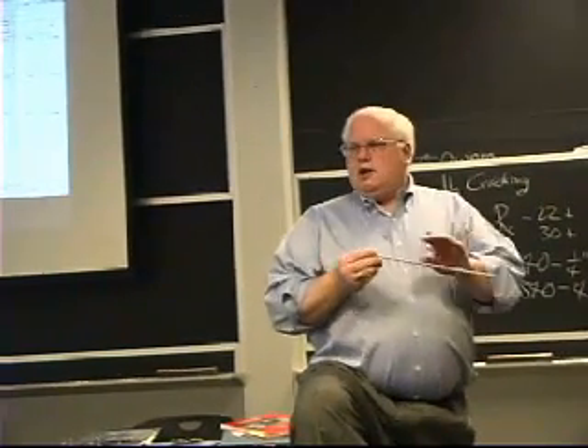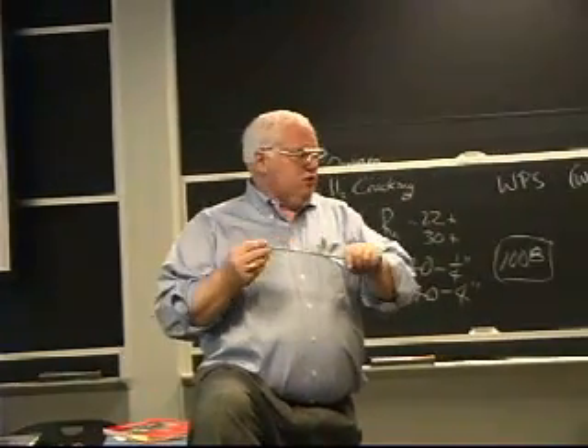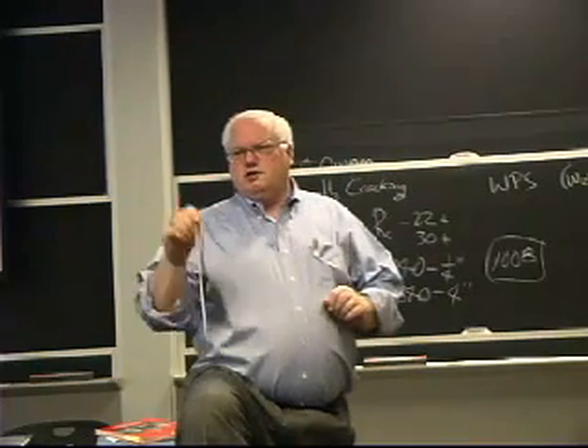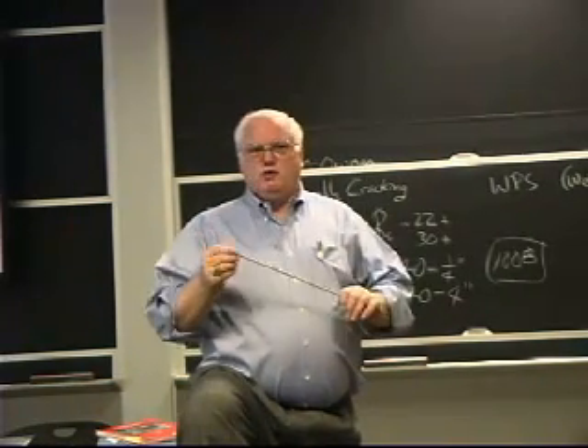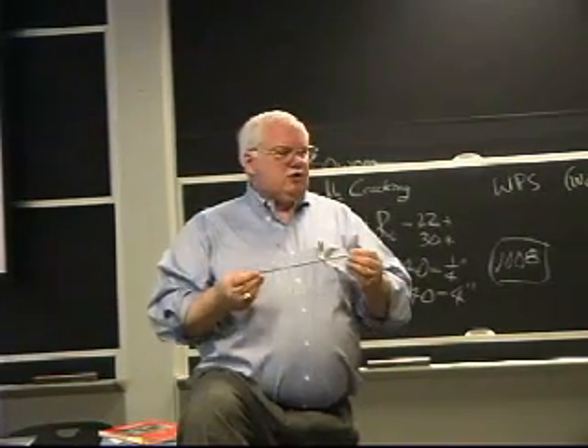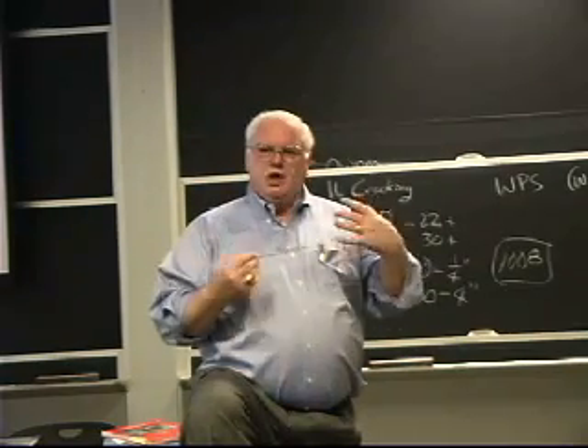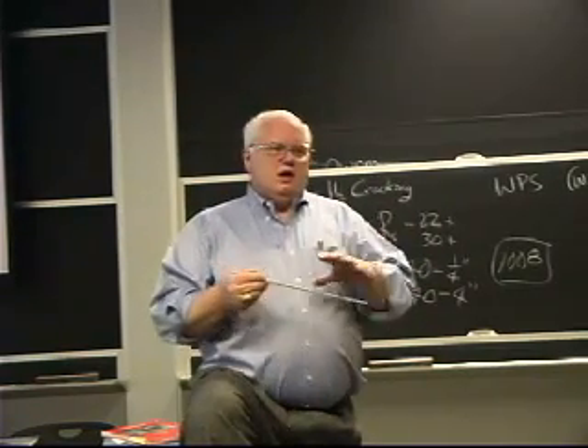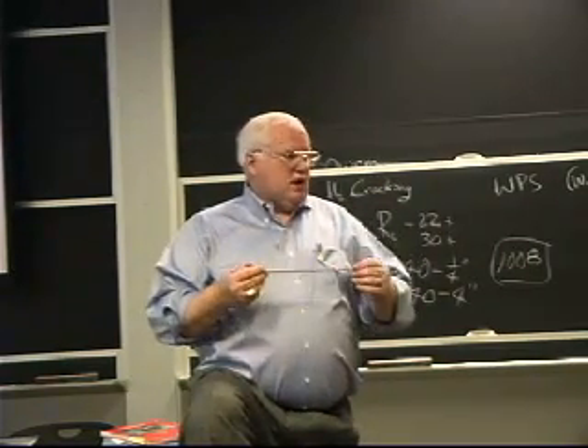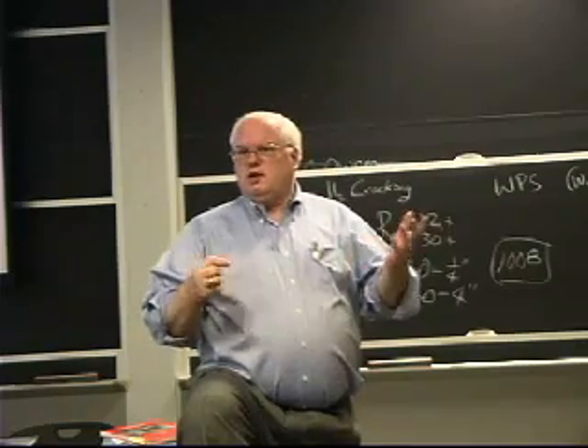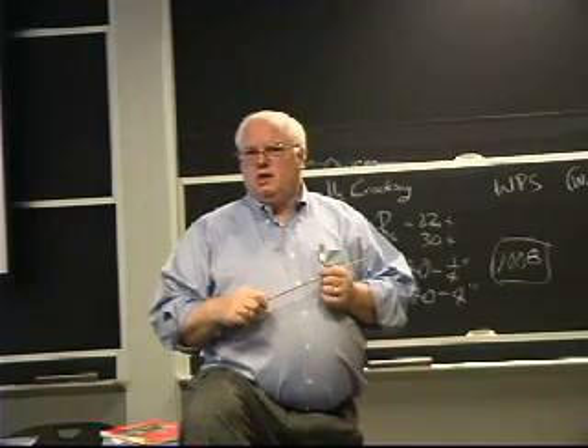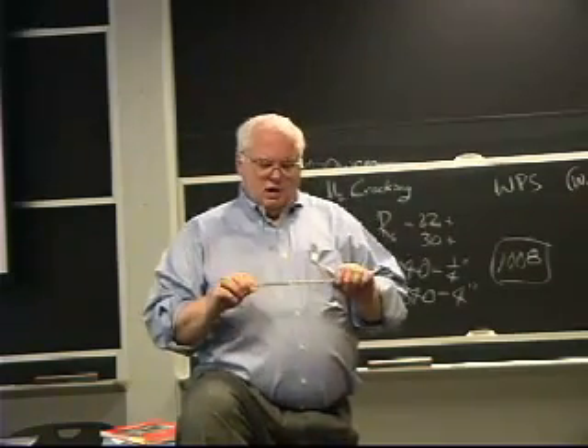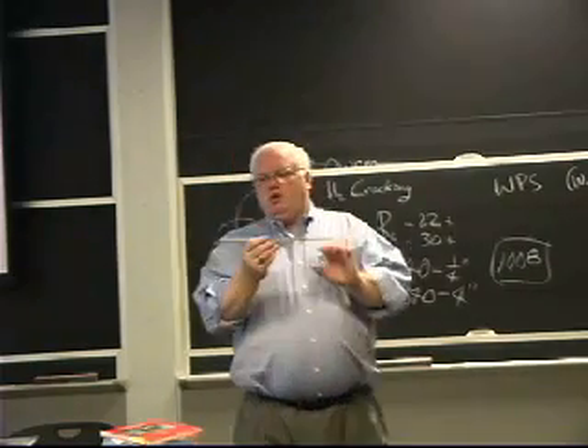But basically, the guys found that if they put a mineral coating on the electrode, and the story is the guy actually stuck it in the mud and welded with a muddy electrode, and he found that the mineral flux provided enough of a shielding atmosphere and a little glass layer on top of the weld to protect it from the nitrogen in the weld, and you got 100% dense weld. And that was the beginning of the ESAB company, and that's what we call mineral-coated electrodes.